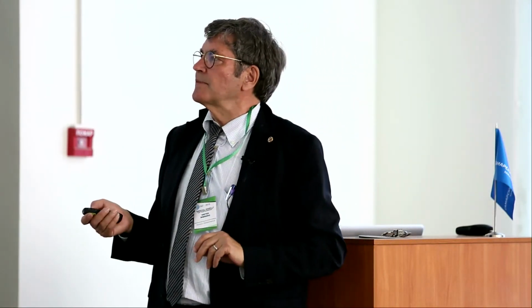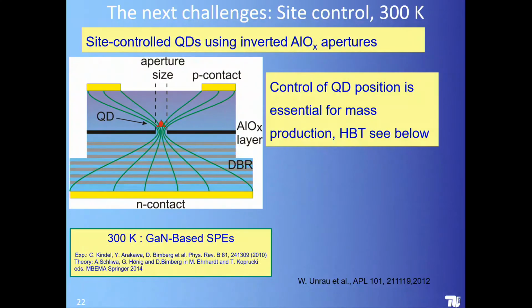Now we did the opposite. We were growing the DBR, fabricating the aluminum oxide, and then did the modeling and found out that on top of such an aperture, you have a strained area, and indium atoms are larger than gallium, so they move automatically towards this hole. Yeah?